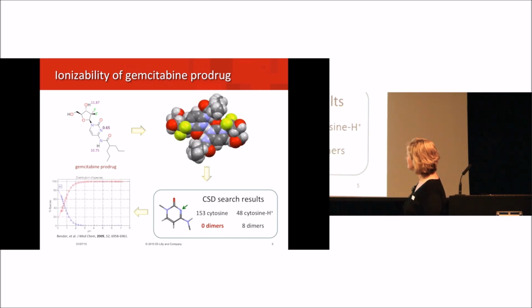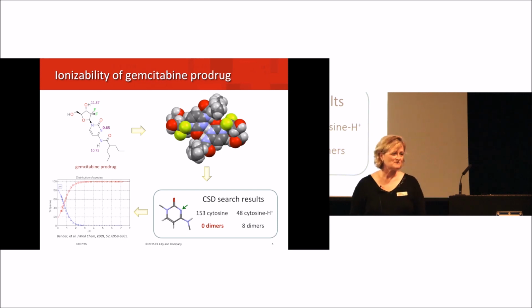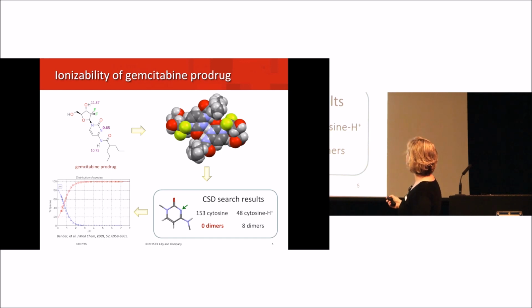And what I was able to show is that when you had protonation, sometimes you formed the dimers. They were actually hemisalts, so you had a charged neutral and an ionized form. But in no instances out of 153 structures did we see the dimer. And so I was able to take this information, backed by the statistics of the CSD, and bring that to my organization, and that basically got our crystallographer to take a second look at the structure, re-refine it, and put the protons in the proper place.